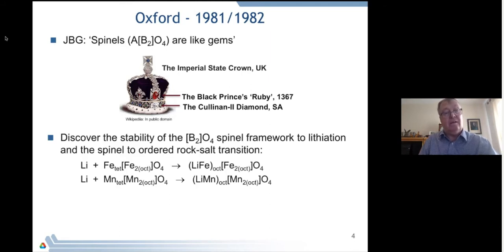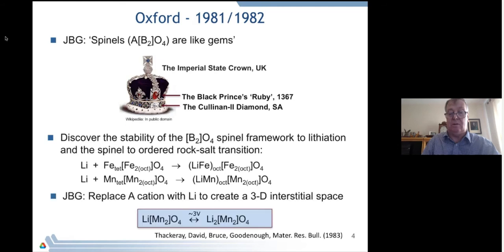But we went ahead and looked at the reactions of lithium with these two Spinel compounds and found that the B2O4 framework of the Spinel structure remained totally intact as lithium was inserted into the Spinel. But in order to create the space, the cations on the tetrahedral sites had to be displaced into octahedral sites.